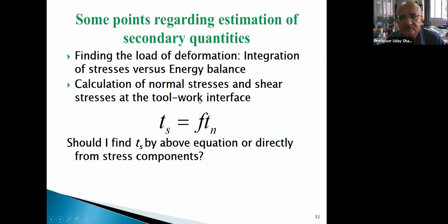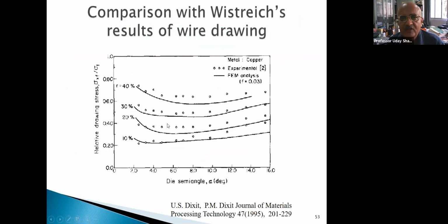Similarly, consider calculation of normal stresses through FEM. You can obtain these stresses by means of proper analysis of the displacements, and once you have obtained the normal stress, then you can find out shear stress: τs equals f times τn. So should I find τs by this equation or directly from stress components? Again, there are fine points, because shear stress is a small quantity compared to normal stress. So a small amount of error in shear stress will have a huge percentage error effect. On the other hand, if you find it based on the normal stress, the error may be less. So these are some results.